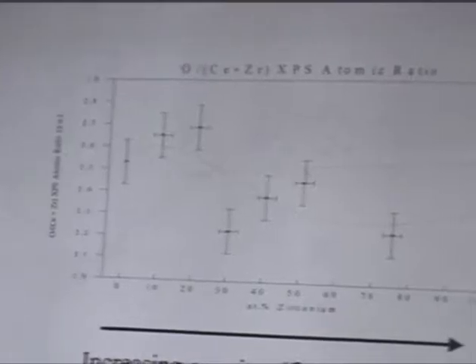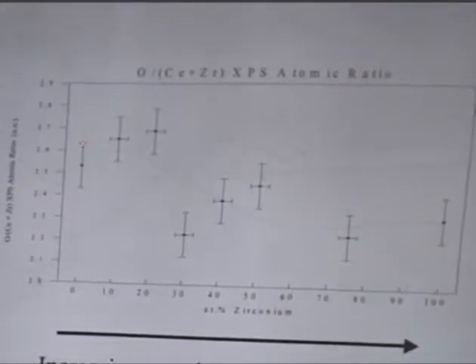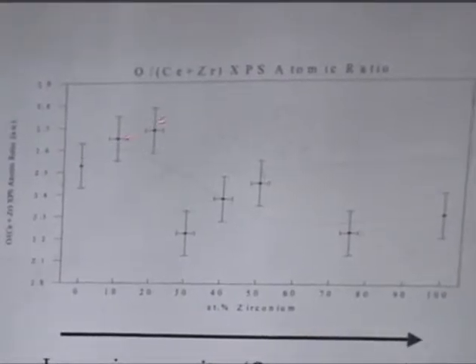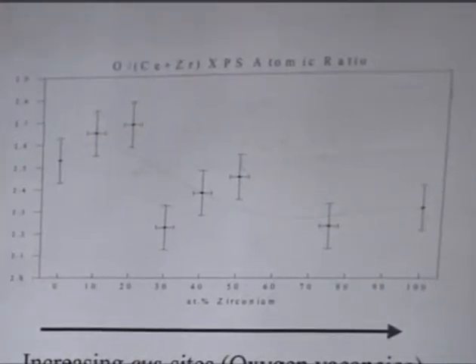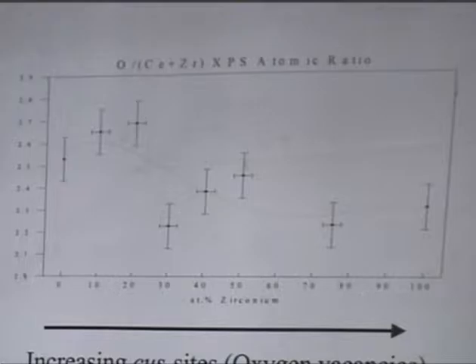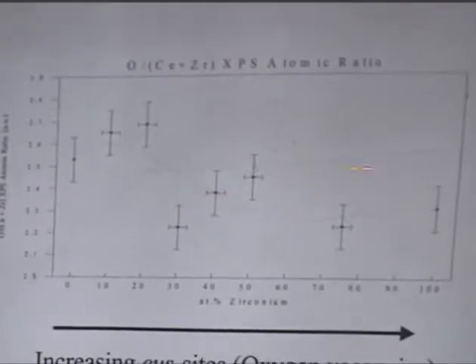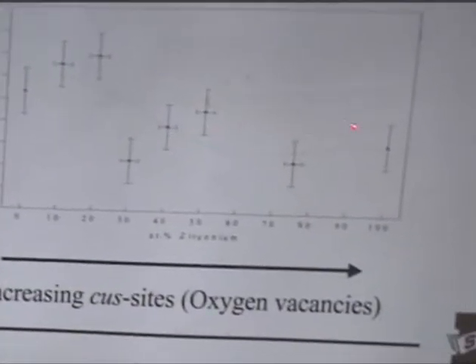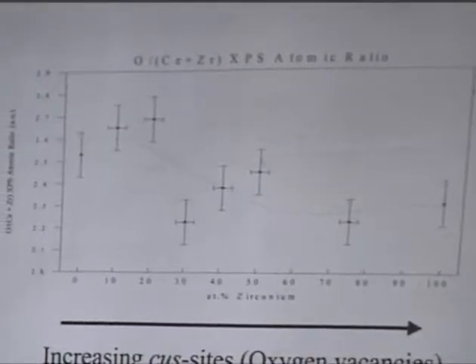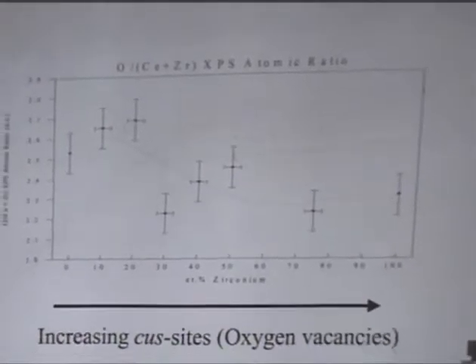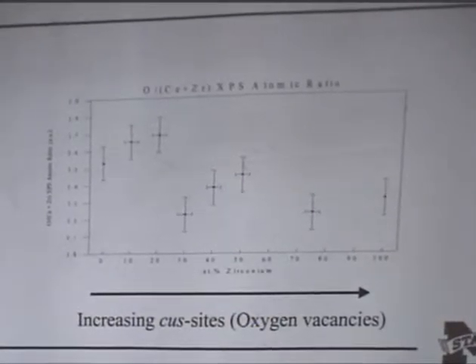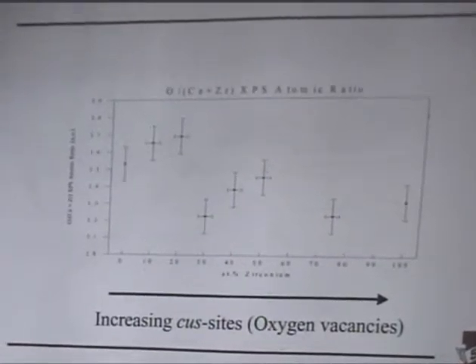We're working right now on replicating these again to see if we can't tighten this up. But the important thing is that we see, under some range of compositions, more oxygen available at the surface for bonding than we do down here. And this is going to be increasingly important as we go through the talk, look at temperature programmed desorption results and so on, as well as speculate some on some binding of the SO2 to the surface.